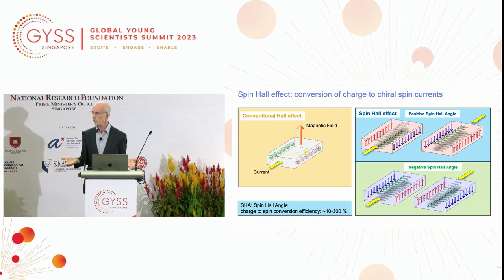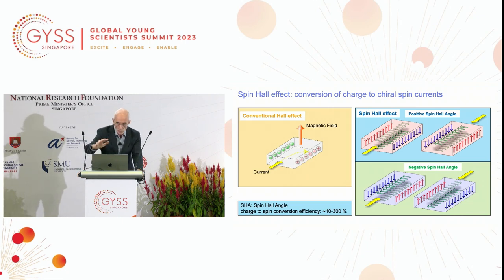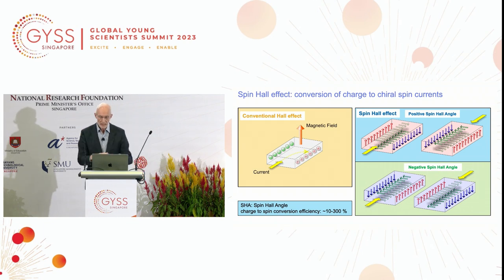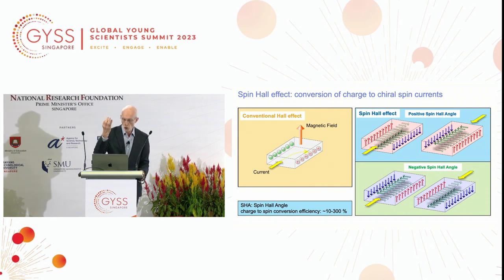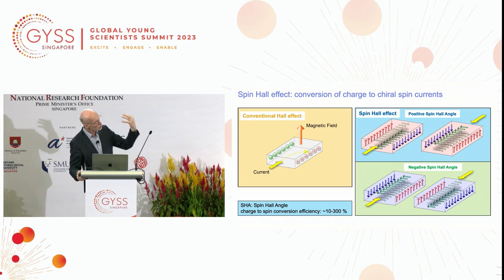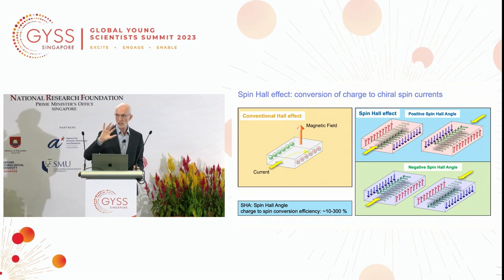First of all, many of you are familiar with the Hall effect. If you pass a current through a non-magnetic material in the presence of a magnetic field, the electrons will suffer from a Lorentz force and they will move either to the left or to the right. So you basically create a transverse voltage which is not spin polarized. Now there's an equivalent effect to the Hall effect called a spin Hall effect. You don't need any magnetic field, but in certain metals where the spin is coupled to the lattice through what is called a spin orbit coupling, you can create a transverse spin current. And this is a chiral phenomenon.